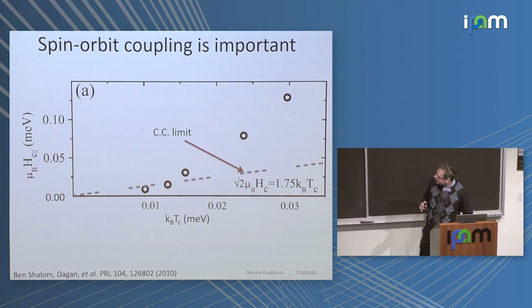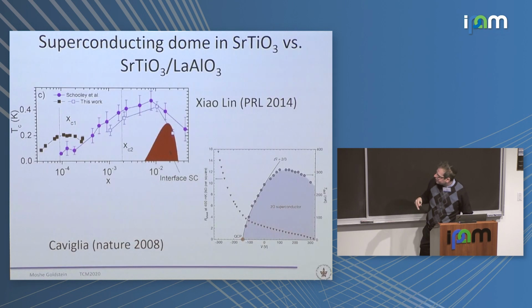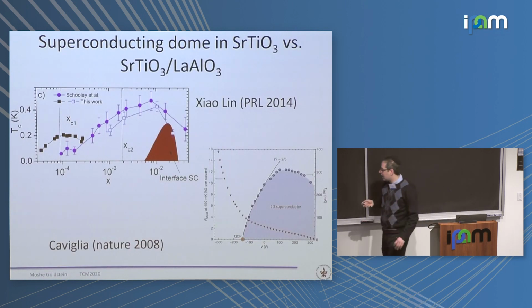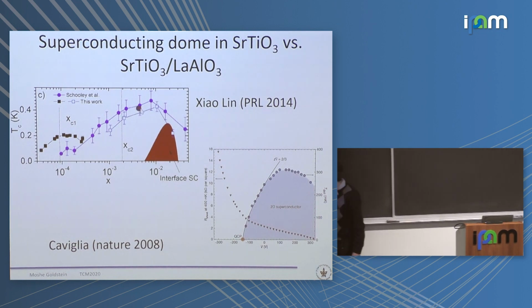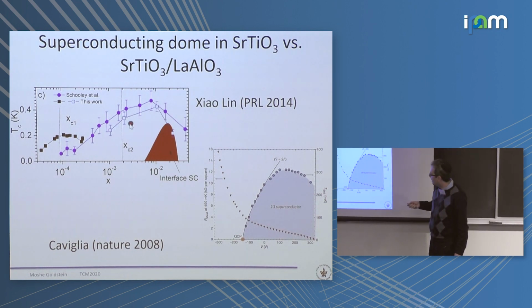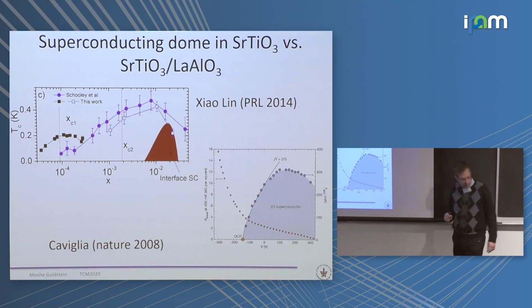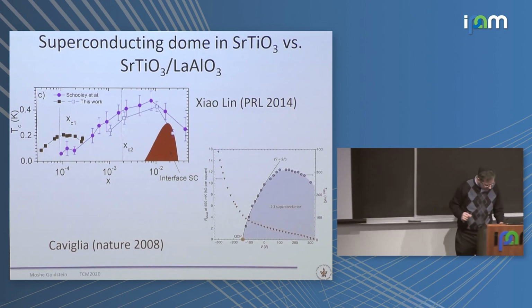And my colleagues have also seen that. Let me skip this. And as I told you, there is also superconducting dome if you dope bulk STO. And you could ask whether or not those are the same. And let me point out that here it's plotted as function of doping, so as function of carrier density. Here it's actually plotted as function of gate voltage, and usually associate gate voltage with carrier density. But as I will show you, actually this is not so simple. So this comparison is not as simple as one might expect.